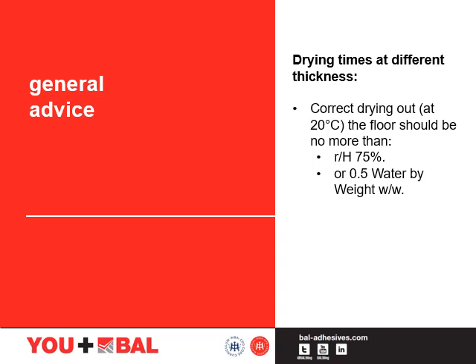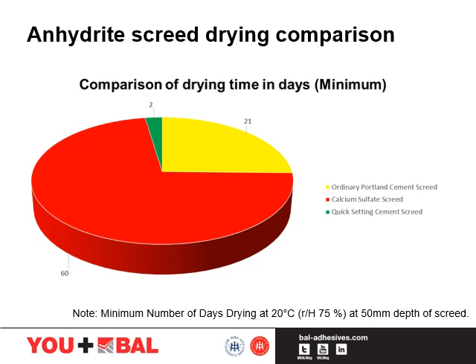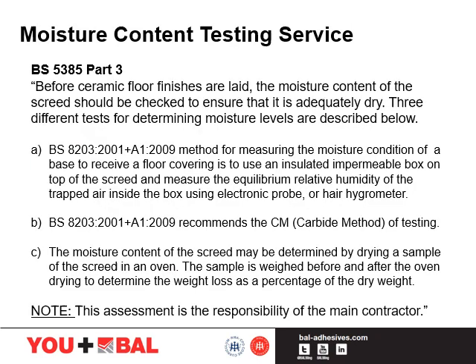The commissioning of the underfloor heating after 15 days or so should also help the screed to dry a bit quicker. As you can see from this pie chart, a 50mm deep anhydrite screed will take a minimum of 60 days to dry prior to tiling. This can be elongated by adverse weather conditions or colder climates.